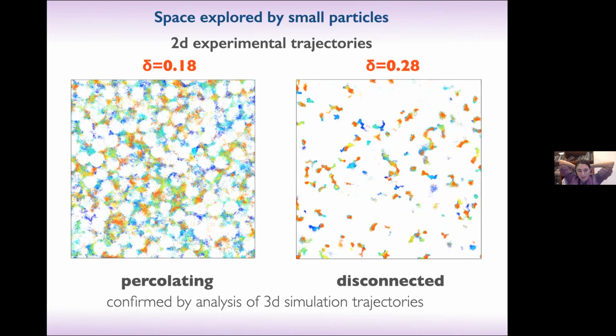So what is happening? I show you this nice picture of the 2D experimental trajectory, and this is more or less what I told you before: at low delta, the particle can diffuse in all the available space. At larger delta, instead, there are these isolated voids, and they become more and more disconnected, and the simulation confirms the same. So why do we get this logarithmic dynamics now?